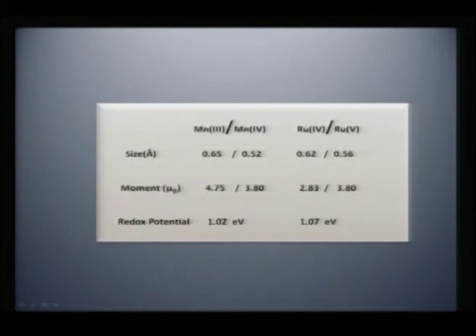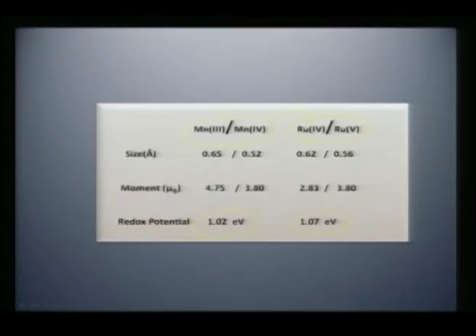Not only that, the ruthenium 4 plus and 5 plus redox is comparable to that of Mn3 plus 4 plus. As a result, you will have a redox mechanism that is happening. So, whenever you substitute ruthenium 4 plus into this Mn3 plus, Mn4 plus pair, you will see part of your ruthenium 4 is promoted to ruthenium 5. As a result, you are clearly providing a double exchange pathway in these manganites.